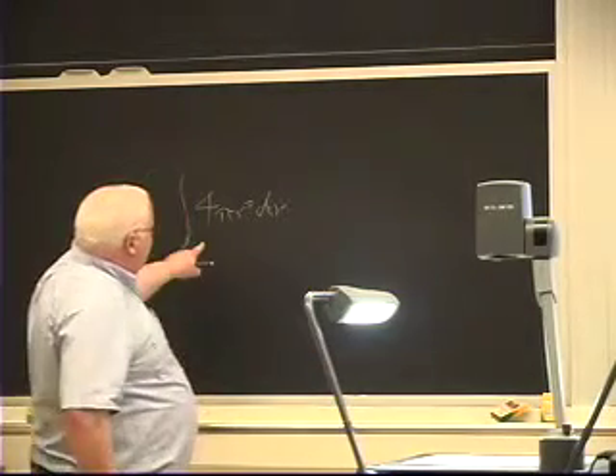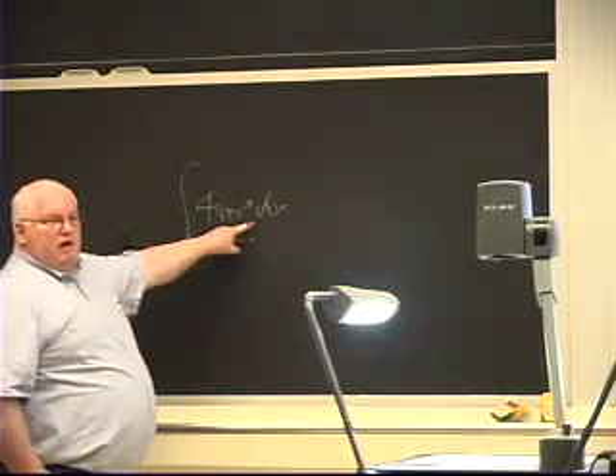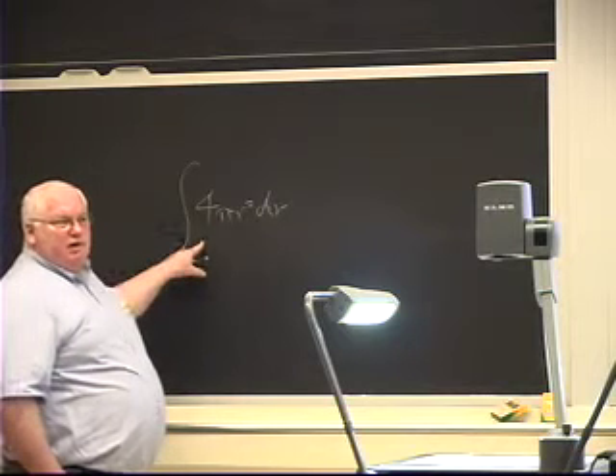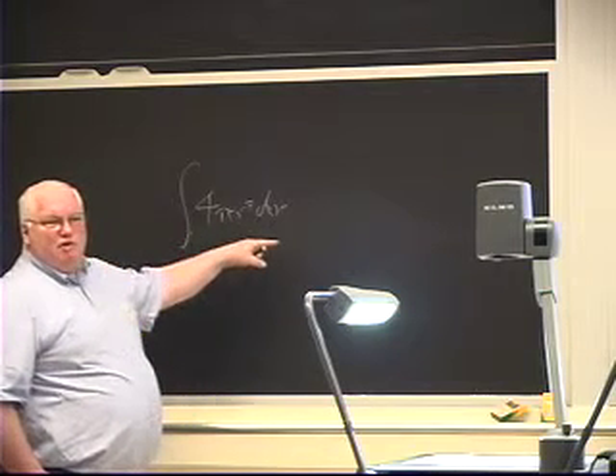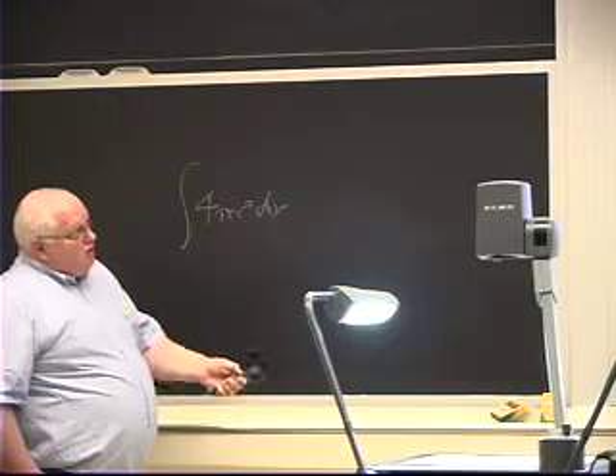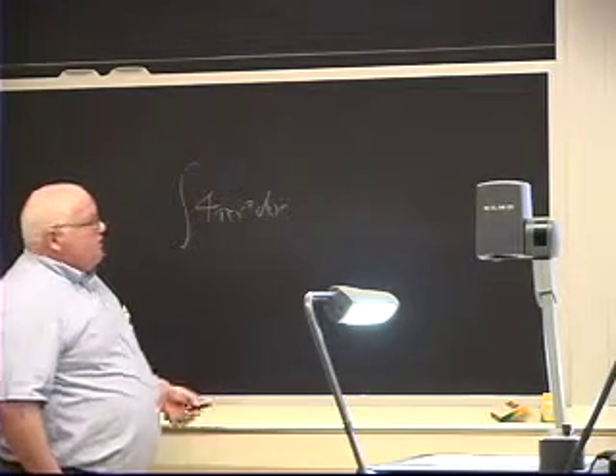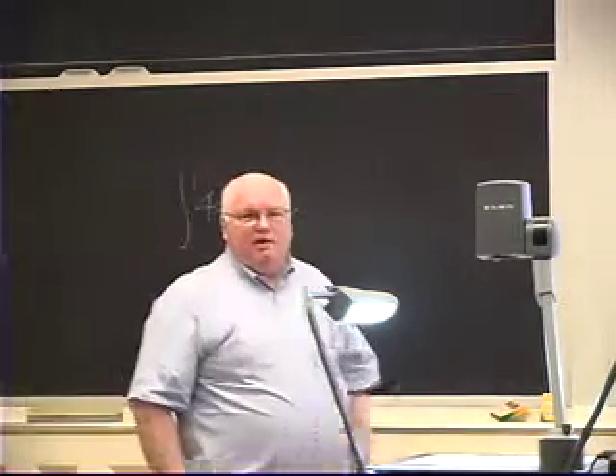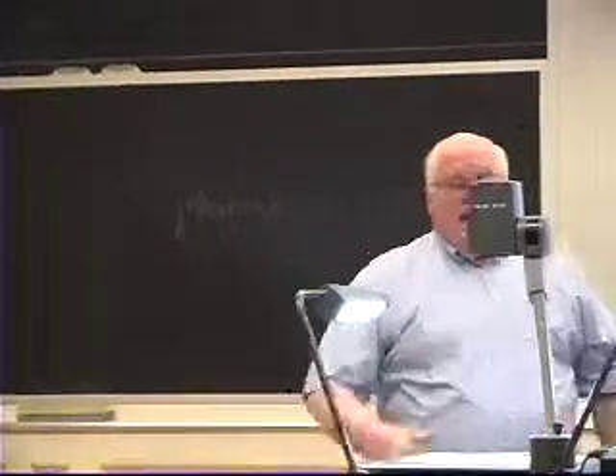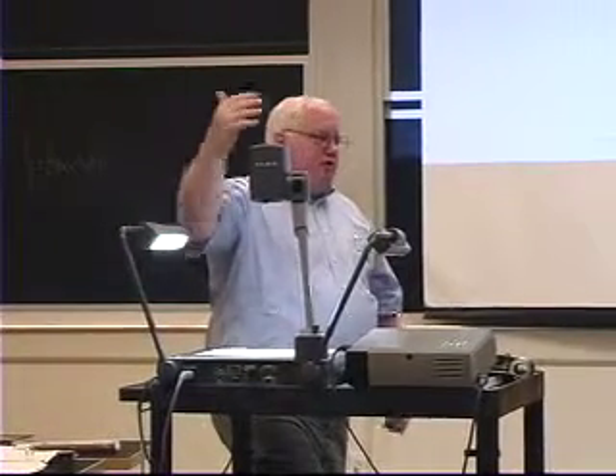I have to take the area of the sphere times the little thickness of that sphere and integrate it over 0 to r. And since r goes further out for the metallic bonds, it turns out if you do that, the area under the curve for metallic bonds is greater. But the point here is metallic bonding reaches out further.